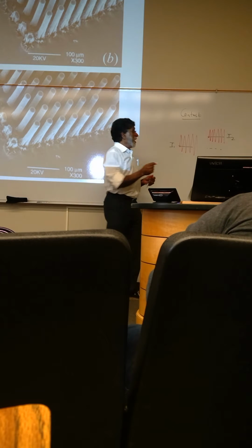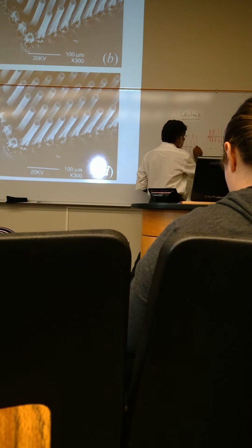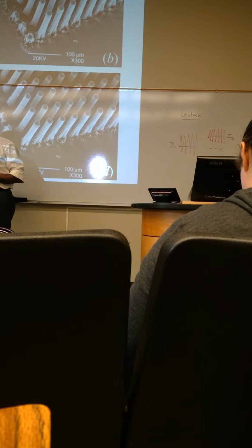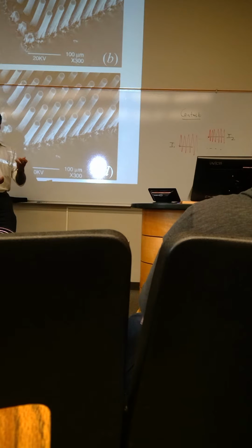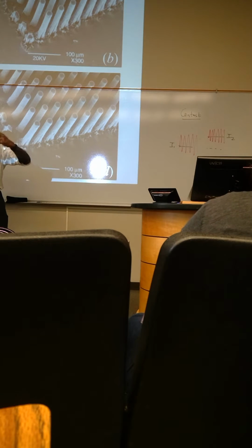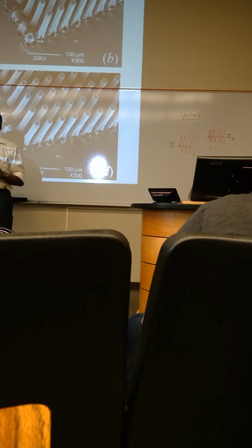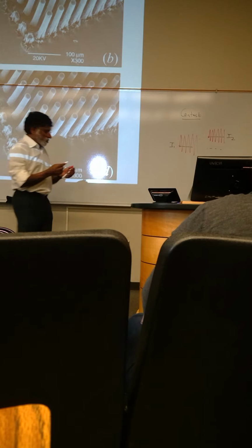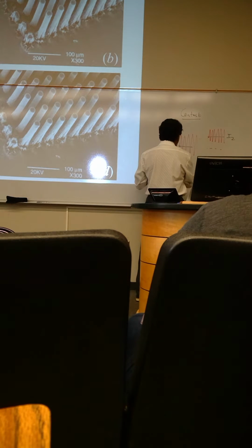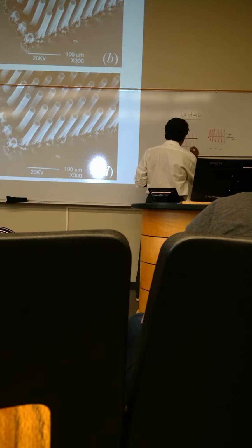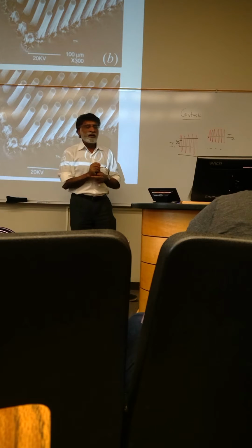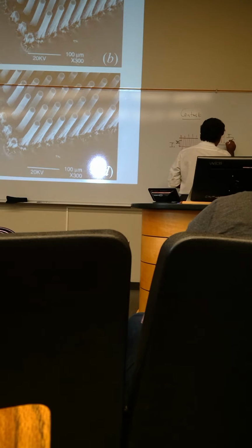Now, if these noise levels overlap, you still won't see any distinction between these two signals. If one is noisy and the other one's also noisy, the two regions, and the noise is significant, then the two signals will overlap. You will not see a difference between the two. So statistically speaking, you want to look at this and this. You're looking at 3 sigma 1, that's a standard deviation, and here also you're looking at 3 sigma 2.